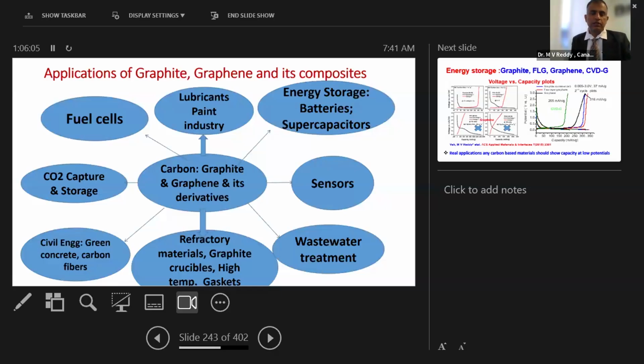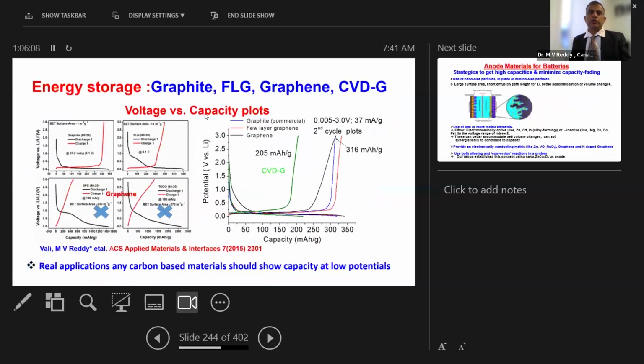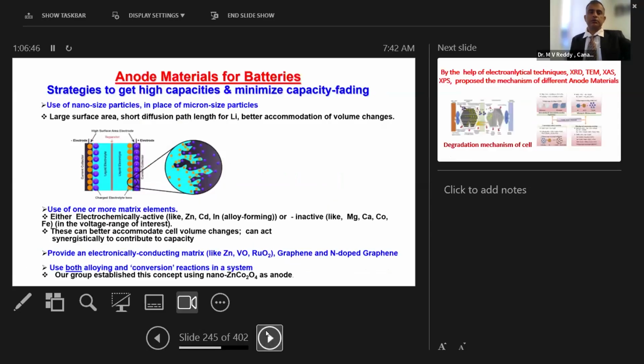I think yesterday another speaker touched on this. So specifically, I'm focusing on energy storage. You may use graphite; this is the typical potential of graphite. For graphene, the bottom two graphs, as you can see, although we get some high capacity, practically this may not be really useful. Graphene alone can't replace graphite. That's why they may use graphene additives, a small amount of graphene to improve electron transport. Graphene alone replacing graphite is not possible, mainly because of the voltage hysteresis, which is the major issue. So quickly, I will go through since I don't have much time.